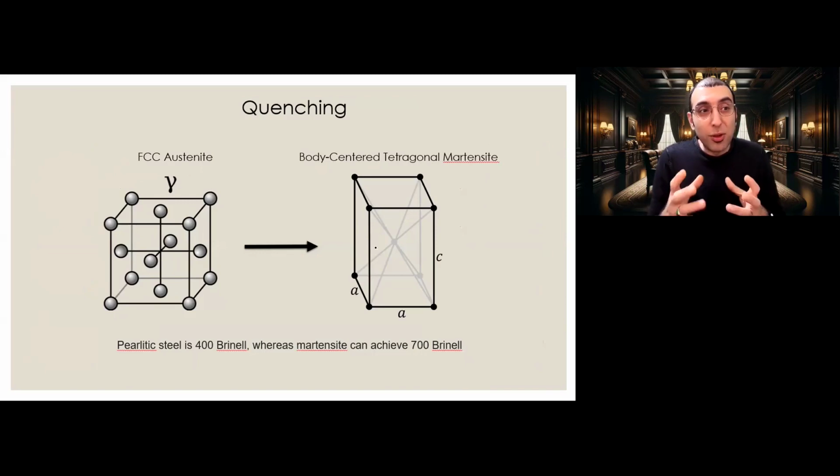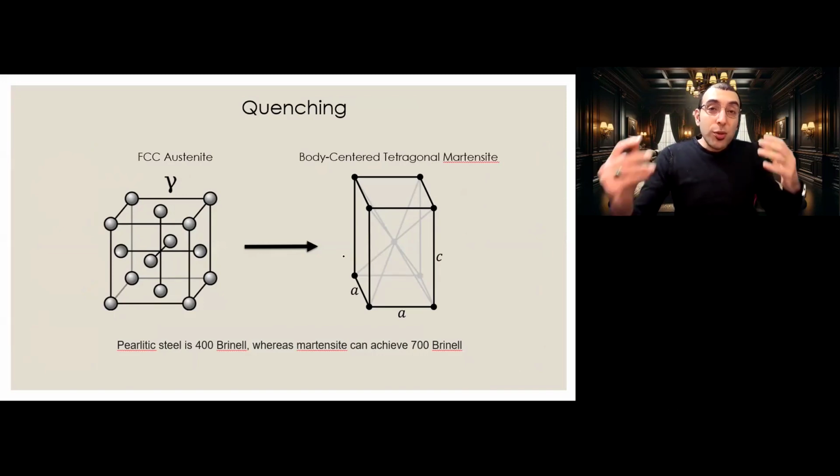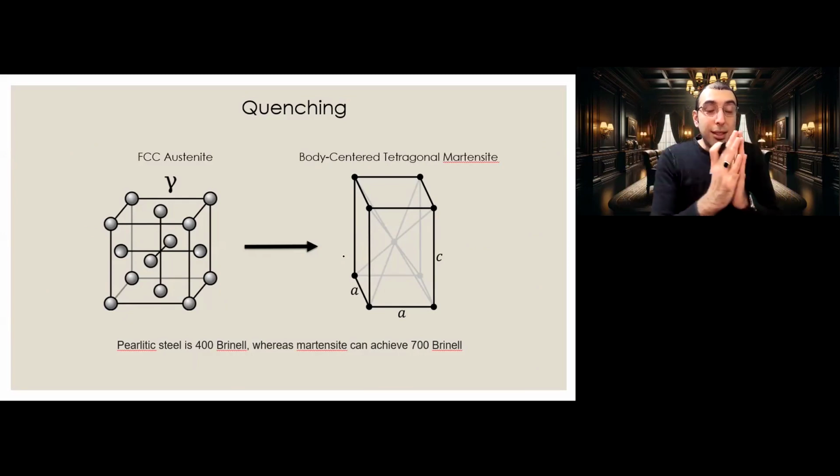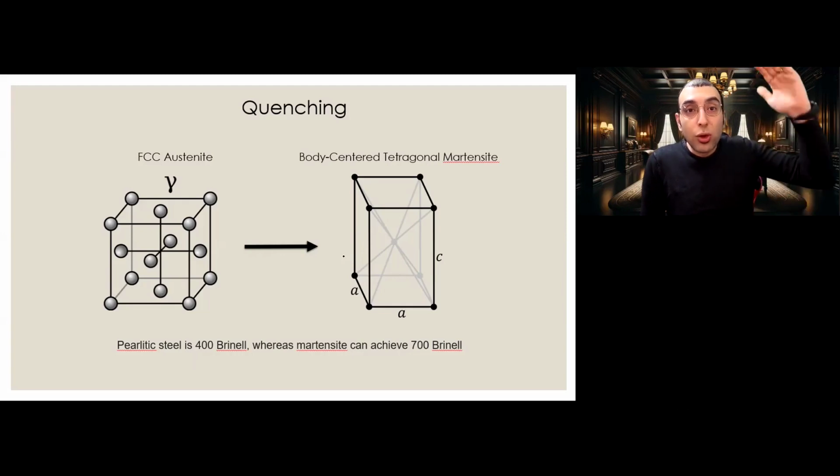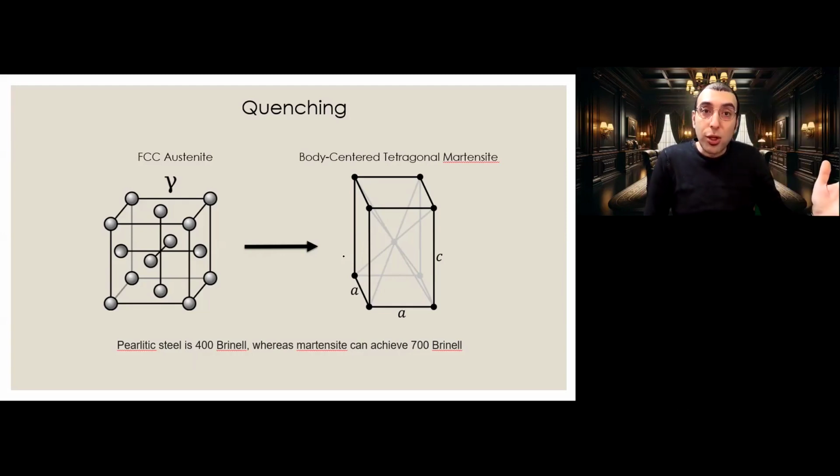So this thermal tension made this shape shift in steel, and this shape shift makes your material, maybe to our advantage, extremely hard. It's the same composition, it's the same structure, you're just changing the cooling rate. If you cool down slow, you get a kind of malleable ferrite plus cementite.